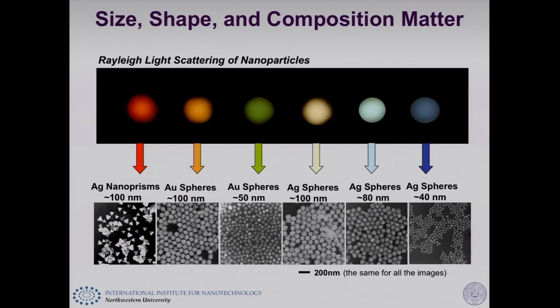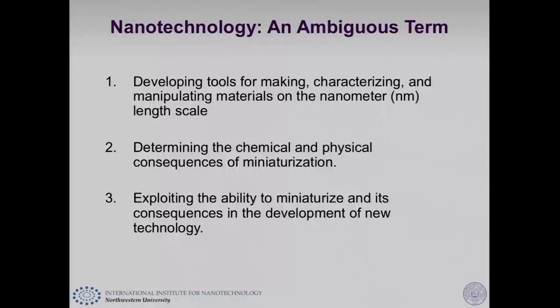If I go to gold, 50 nanometer structures, I get a green hue. And if I go to 100 nanometer particles, I get orange. And now if I change the shape of the gold, or in the silver in this case, they're silver nanoprisms, I get red. So that's kind of neat. With one material, I can manipulate properties systematically simply by adjusting size and shape. And that's a new and very powerful concept, and very important if you're thinking about ultimately discovering new materials and developing new technologies. So the third part of this is in fact doing that.